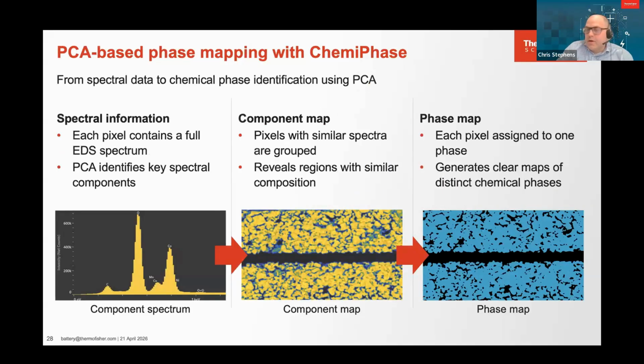So going a little bit further, one of the techniques we've introduced is what we call ChemiPhase. And this is loosely based on a so-called PCA or principal component approach. If you think about it, when you analyze a map over a sample, every single pixel in that map will have a full spectrum behind it. So it's a complicated multi-dimensional data set. And using a PCA or principal component type routine, you can really reduce down the complexity of that.